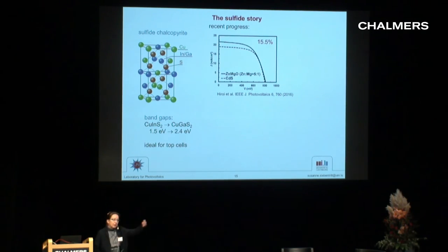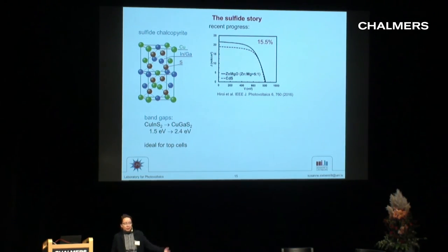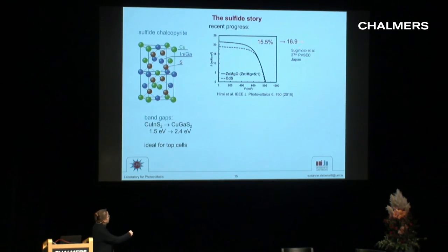And these sulfide solar cells have been investigated for a long time, and they got around 10% efficiency, and then people lost interest and stopped working on these solar cells. But recently, published last year, a company in Japan, Solar Frontier, looked into this material again, and they got a very good efficiency of 15.5%. And at the last conference, they showed almost 17% for these sulfide solar cells.